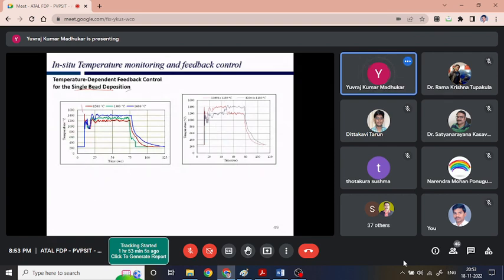Here we could see we are depositing low alloy steel. We are able to hold the temperature. We are measuring it nearly 10 mm behind the arc, and we are able to hold the temperature at 1200 degrees centigrade, 1300 degrees centigrade, 1400 degrees centigrade, or even during the deposition of a bead itself, we are able to control the temperature using the deposition itself. From 1400 to 1200 or 1200 to 1400 centigrade, we are able to regulate it.